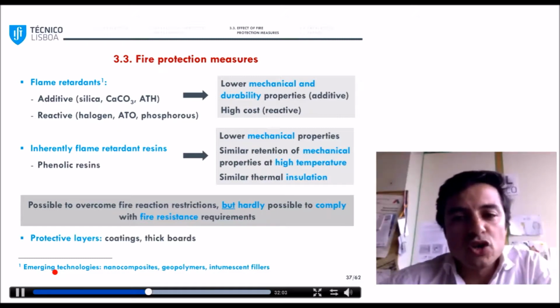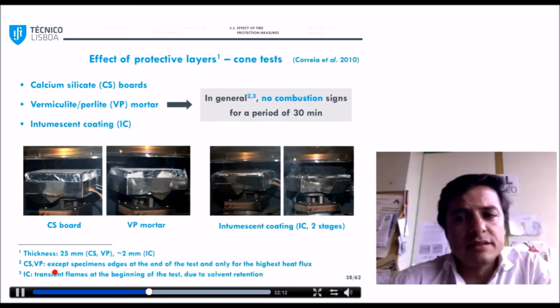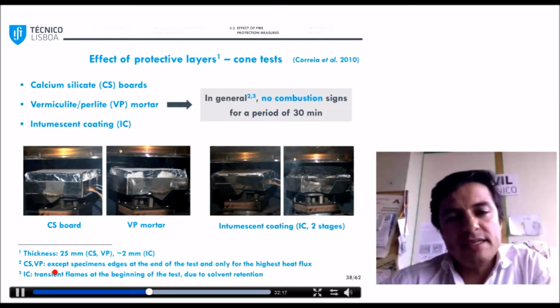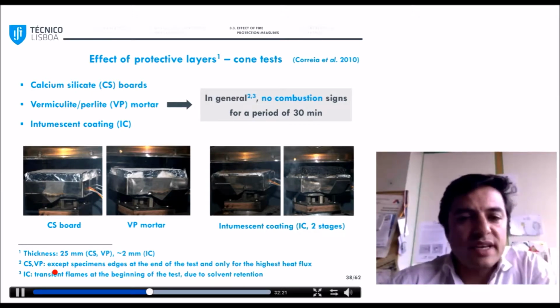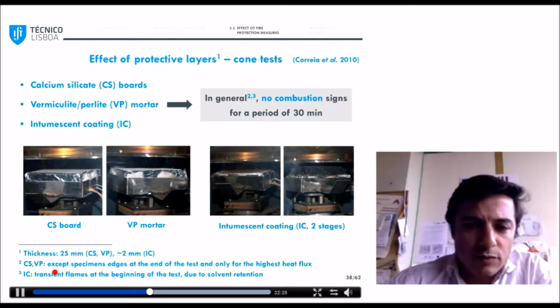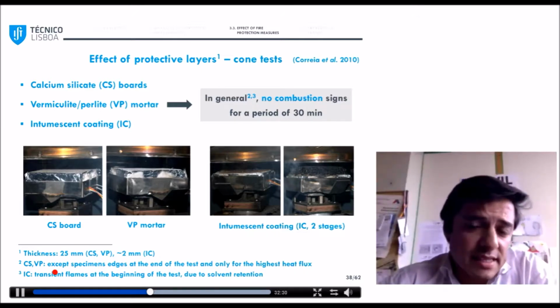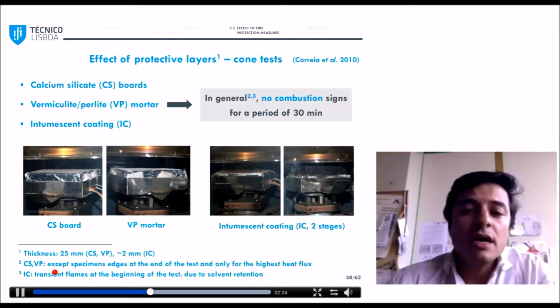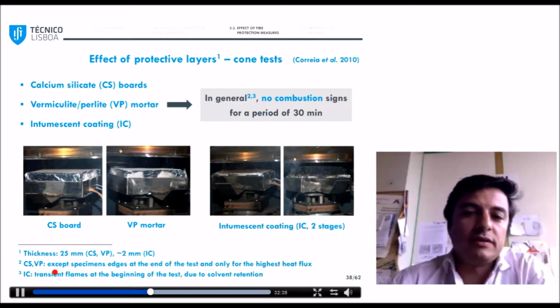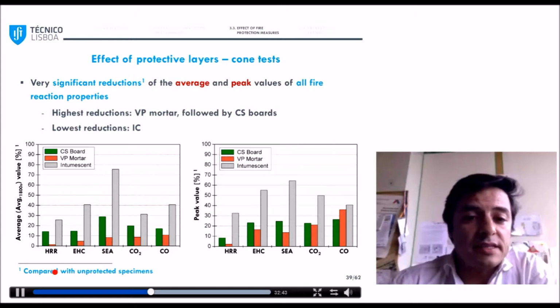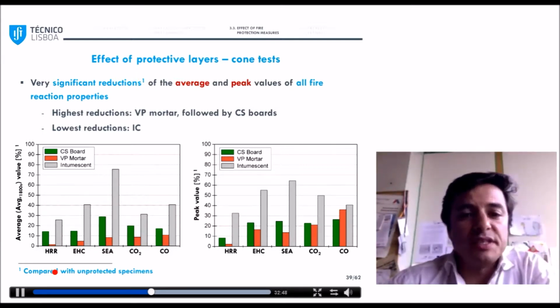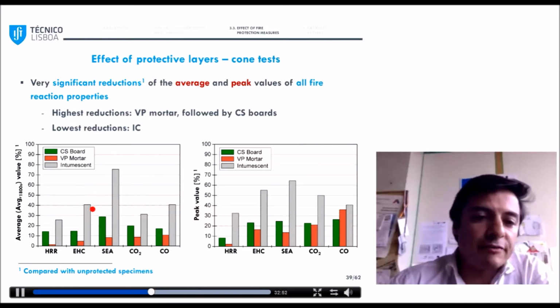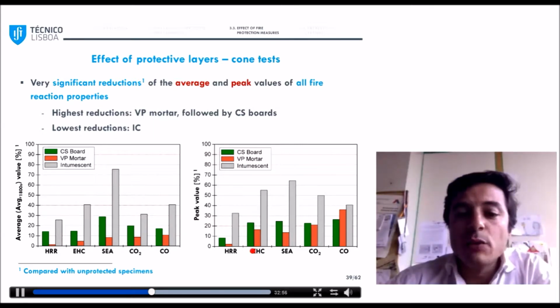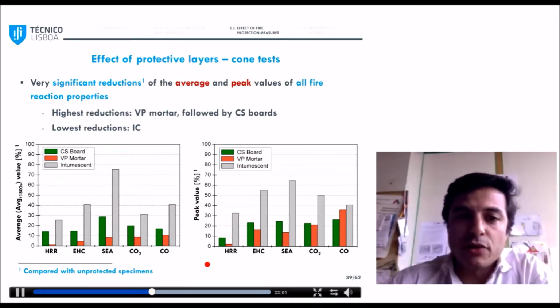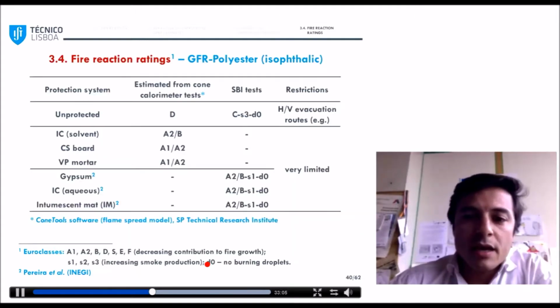So we may need to seek an alternative approach consisting of using protective layers, either coatings or thick boards. So using this alternative approach, we did a set of new tests in the cone calorimeter in GFRP laminates protected with three systems: calcium silicate boards, lightweight mortar, and an intumescent coating. And in these tests, since we are basically testing the protection materials, no signs of combustion were observed during the 30 minutes of testing. And therefore, as you can see in these two figures, the previous fire reaction properties I showed before, their average values that you see in the left picture and the maximum values that you see in the right picture, they were all very significantly reduced, especially for the thicker protections with mortar and with boards.